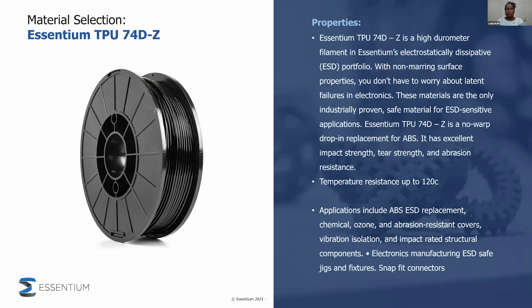So if you're looking for an ABS alternative, TPU 74D, both in its ESD and non-ESD formulations, is a great option and replacement. This material also has temperature resistance up to 120 degrees Celsius. Applications for this material include, like I mentioned, ABS replacement, ESD replacement. The chemical resistance makes it great for multiple cycles of exposure to chemicals, ozone, and abrasive environments. The elastomeric properties also allow cushioning for vibration dampening and for impact rated structural components. Being ESD safe, it can also be used to hold and enclose electronics, like I mentioned before, and create ESD safe jigs and fixtures and snap fit connections.